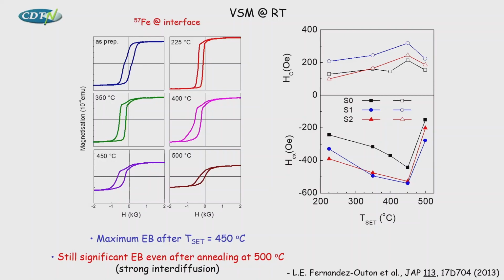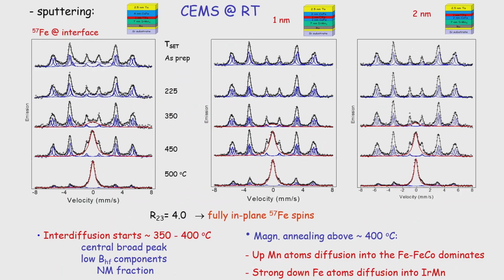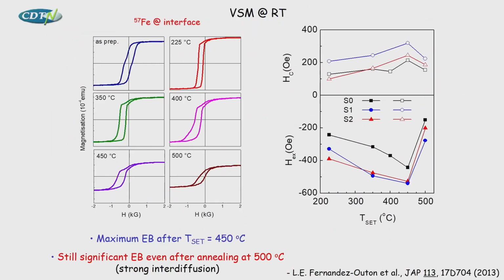No, because you said that there is a diffusion. But if you look at Mossbauer, the spectra are the same here? But the diffusion starts at what temperature? 350. Okay, you start to see diffusion here, but here you almost kill the magnetic phase, but the exchange bias is there, it is actually the maximum. Okay, the remaining material is coupled.